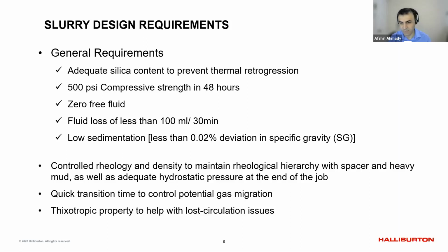Rheology needs to be controlled, and density, both of them, to maintain the rheological hierarchy, especially when you have heavy mud in the hole. That was another restriction for this design. And transition time. Raf mentioned that one just briefly. Transition time is impacted by different variables, and one of them is density. How is the hydrostatic of the cement? It's coming from the column of the cement and also from the density of the cement. So transition time can also be impacted by reducing the density of the cement, at the same time reducing the rheology.